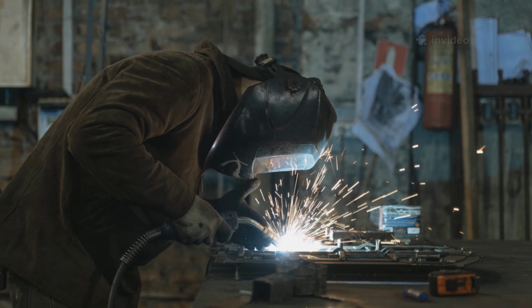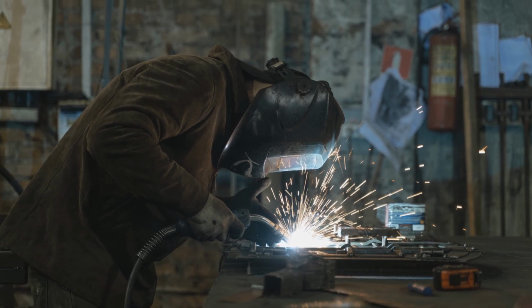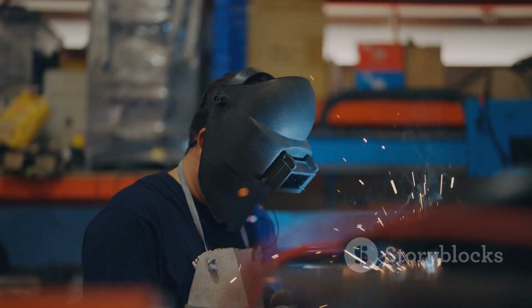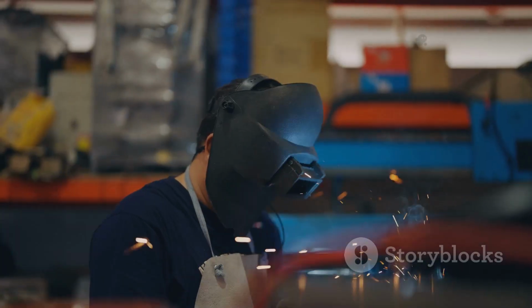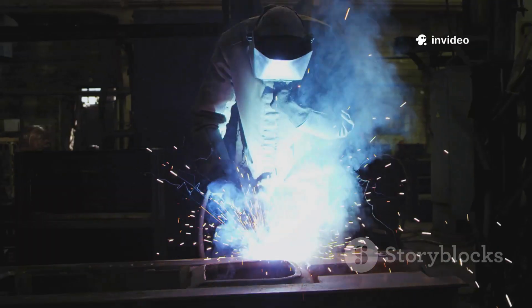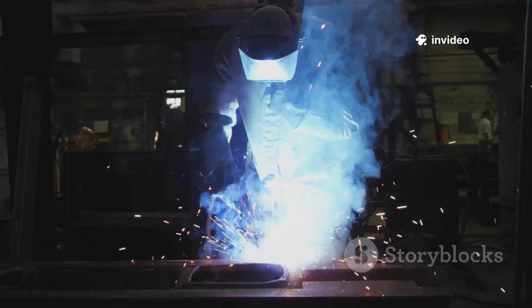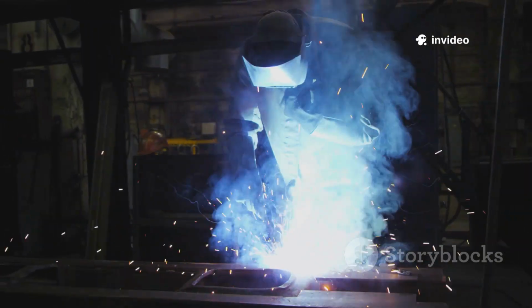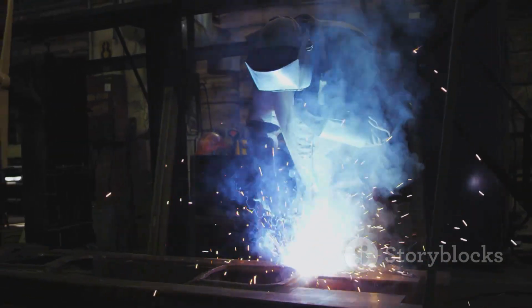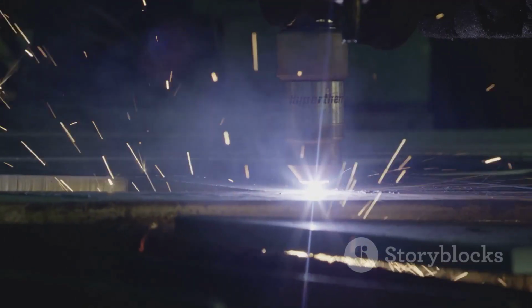Different metals behave differently under the intense heat of welding. Steel is, honestly, pretty straightforward to weld, but other metals need special care. Aluminium, for instance, has excellent thermal conductivity, so it pulls heat away from the weld puddle really quickly. This means you need to use a lot more heat to get it to melt. It also has a thick oxide layer on its surface that you have to clean off just before welding.